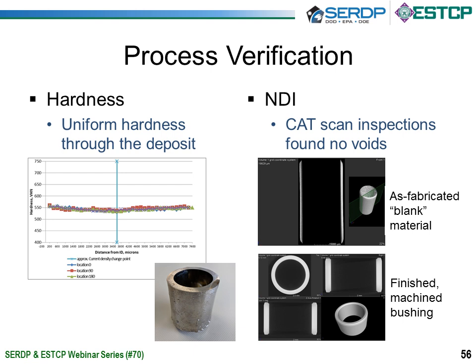In terms of other process verification techniques, some NDI has been performed on these electroforms, CAT scans primarily. We have found no voids in the material, and the analyses have been done both on the as-fabricated blank materials and on the fully machined bushings. I think the voxel size for the blank material was around 15 microns, maybe a little lower for the fully machined bushing. So certainly any voids that are in there are smaller than that.